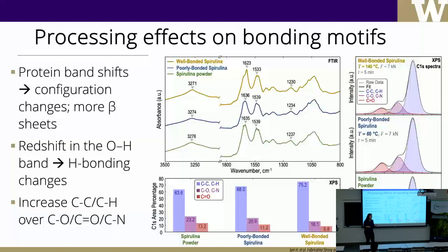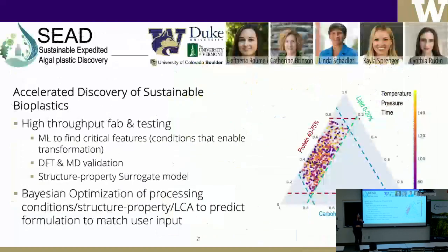So from all of this, what we can say is that our hydrogen bonding is not identical. So there is some change there, even though arguably minimal. There is something happening actually way more significant in our protein domain because of the shape of the peaks. And then there are also some changes even in our covalent bonds, where we have changing ratios between the different bonds over here. So I really thought that it would have been way easier, but it is very complicated, especially if you think of our slide 1 with all of the characterization, where you have 5 different monosaccharides building up your polysaccharides. You have 5 bins in your proteins, where you have different amino acid sequences in all of those. Then you have some lipids that actually play a significant role, and it's all over the place. Unfortunately, to my surprise, we could not come up with a reliable conclusion.